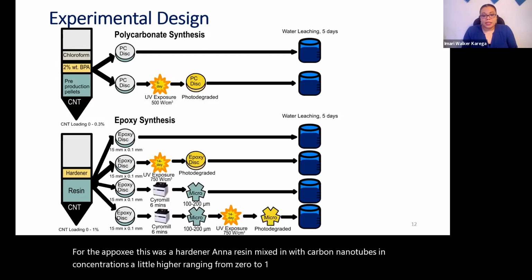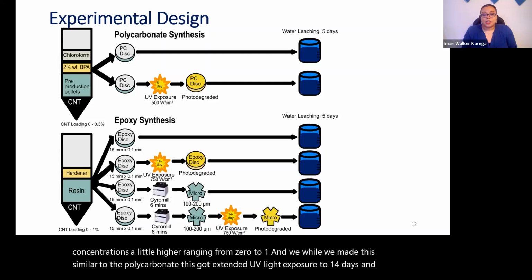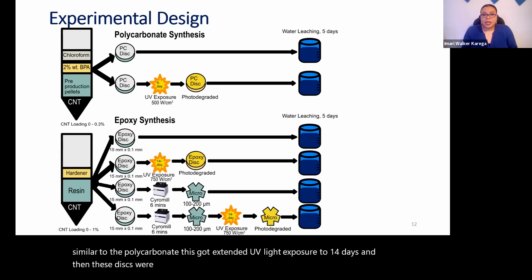While discs were made similar to the polycarbonate, these received extended UV light exposure of 14 days. The discs were also cryomilled to create microplastics around 150 micrometers in diameter.